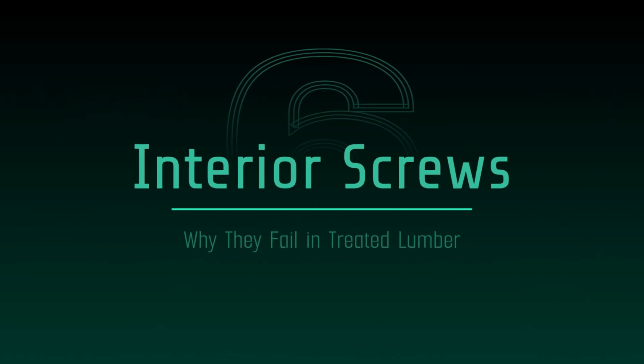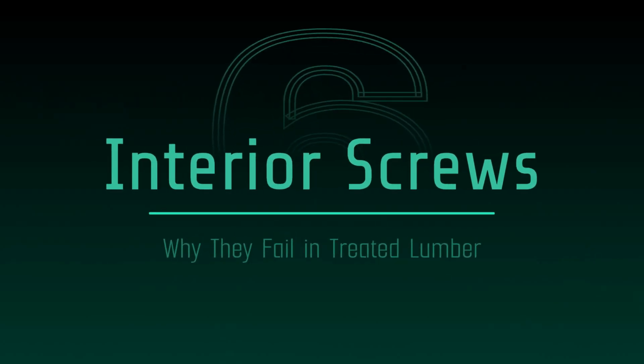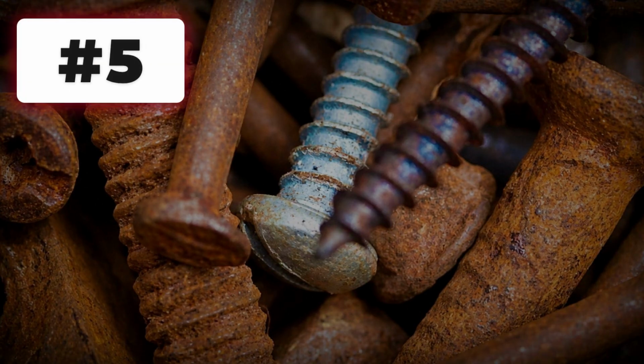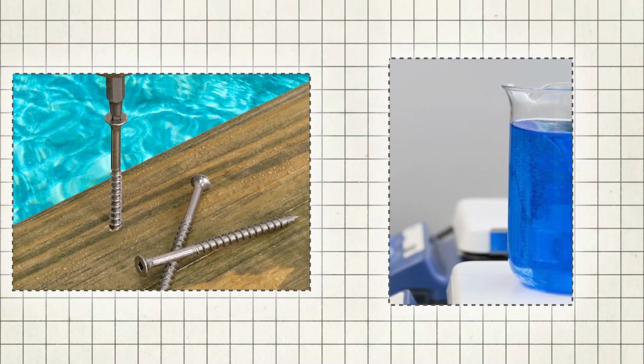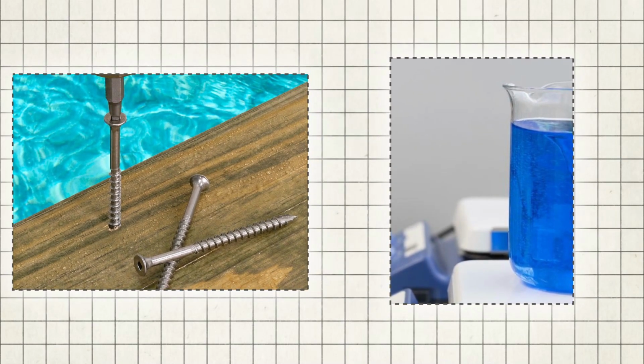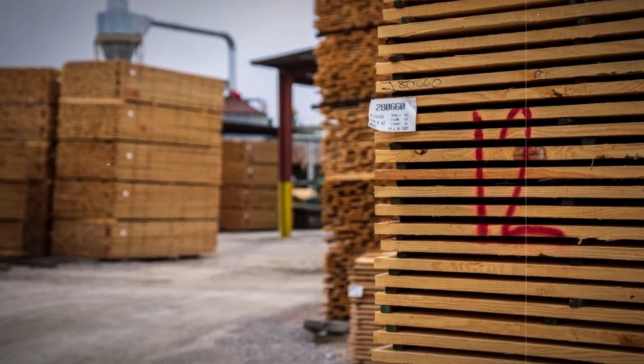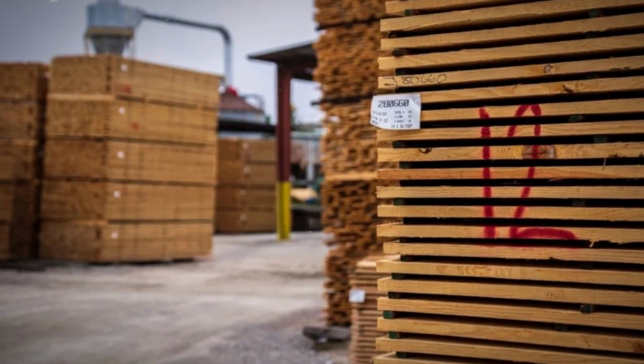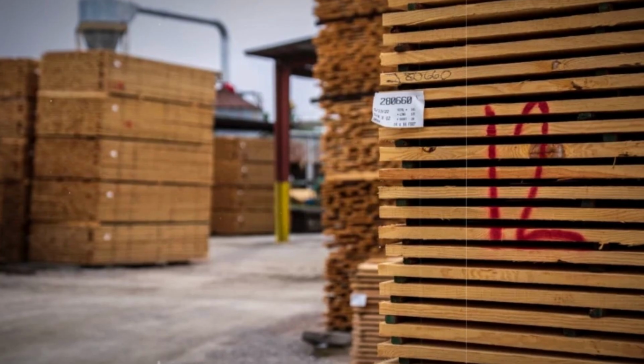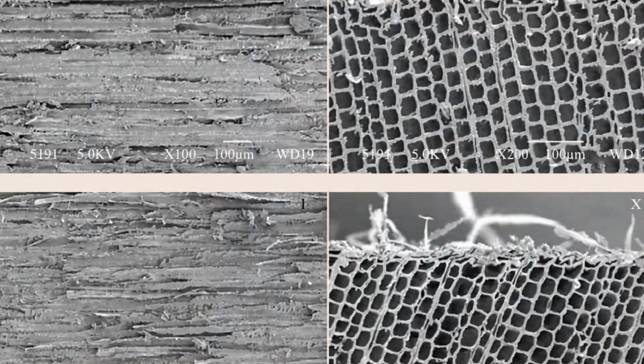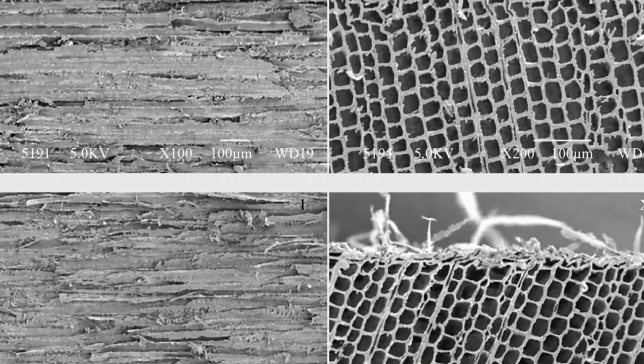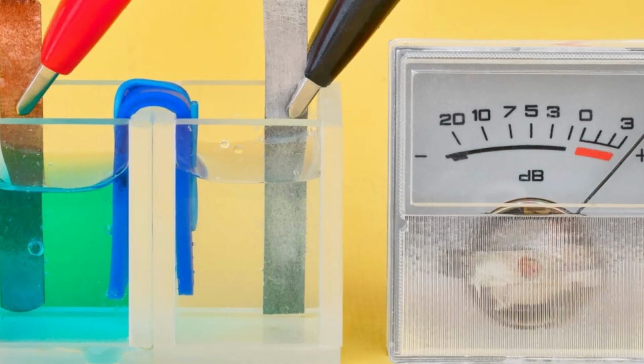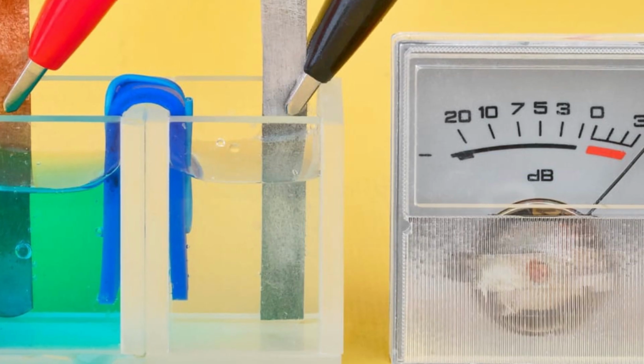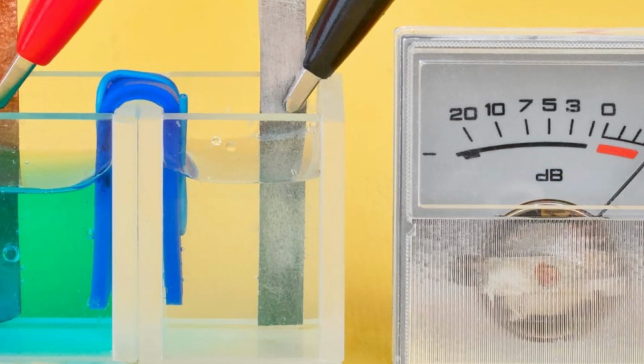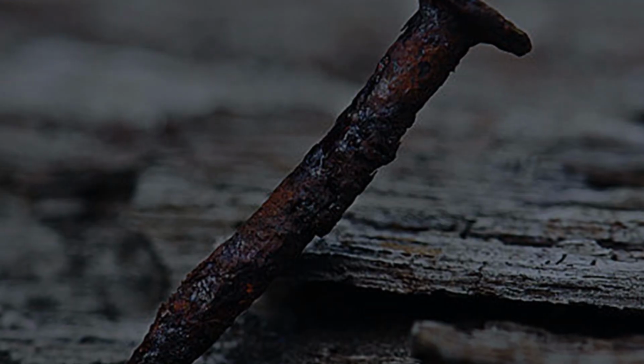Number 6. The interior screw in exterior lumber. Number 5. The lifetime coating that isn't. Start with number 6, because this one is chemistry, not marketing. In 2004, the EPA phased out CCA-treated lumber for residential use. What replaced it, ACQ and copper azole, packs far more copper into the wood. Copper against zinc or steel in the presence of moisture creates a galvanic cell. The wood starts eating the fastener.